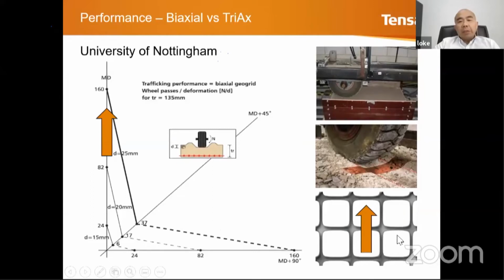So here's the test. We run the wheel loading in this direction over the geogrids. You can see that the 160 means the number of passes, and 25 millimeters is the rut depth. Let's look at this line. It means that I need to run 24 passes to give me a rut depth of 15 millimeters.